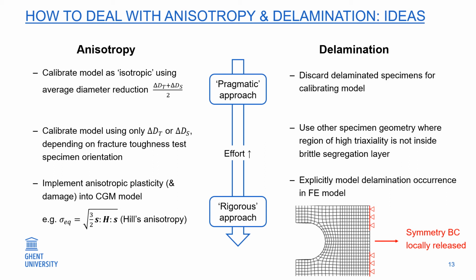The third alternative is to explicitly model anisotropic plasticity into the damage model, requiring more tensile tests in different directions. Concerning delaminations, we could try to calibrate the model using only specimens that do not show delaminations. Or we could use another specimen geometry, where high triaxiality values are reached in a region further away from the segregation layer. The other option is to explicitly model the occurrence of delamination by locally releasing the symmetry boundary condition. We are currently investigating which of these approaches to follow, keeping in mind the balance between work effort and satisfying results.